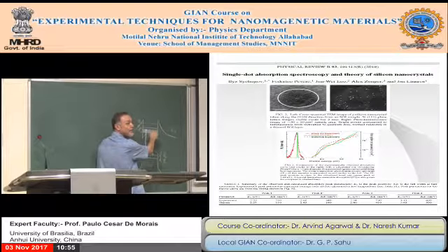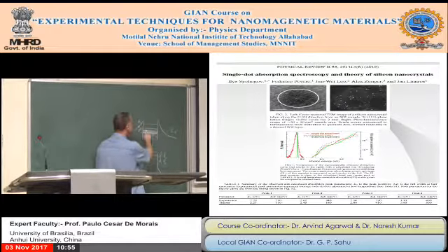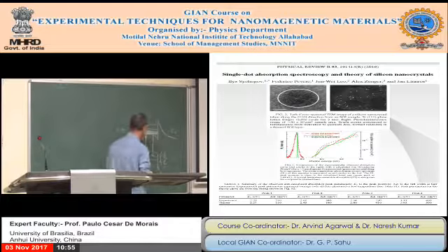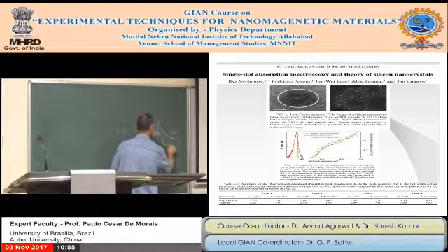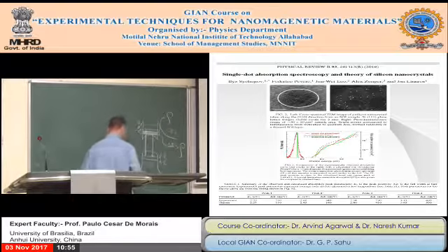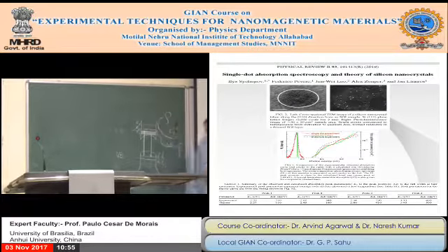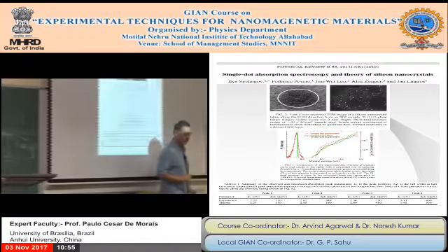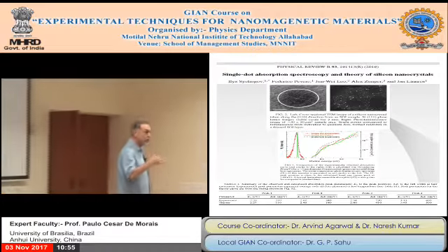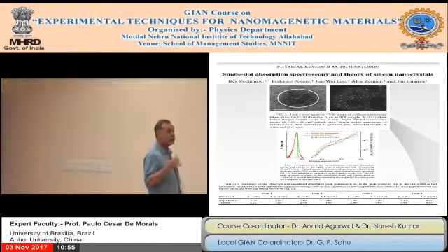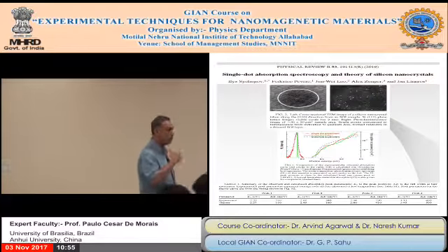It is occupied. So it has to go to the top of the Fermi level. So this difference in energy scales with the charge density inside. This is called Stokes shift. So in semiconductor quantum dots, no matter what the shape is, this is the case.